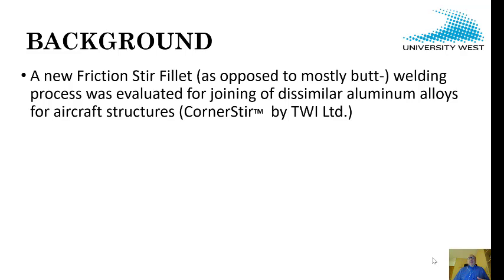So the approach was to weld from the inside, not from the outside, and using a new friction stir fillet weld. Again, this is a different process. I think in my life I've seen 99% of the papers all written on butt welding and lap welding, but this is fillet welding. And not only that, but it's about dissimilar alloy, so it makes it very, very interesting. The process is being trademarked by TWI as corner stir process.